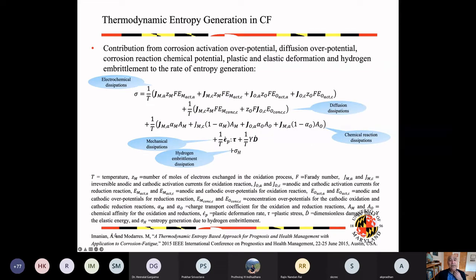So with that, this is another formula which shows the relationship between two different entropies, corrosion and fatigue. Each of the terms is an amount of entropy generation, and this shows the force and the flux of each of them. They are all defined here. For instance, the flux is measured by the overpotential measurement. Essentially, it is the potential in an electrochemical dissipation and oxidation. We can always measure the amount of current and the amount of flux very easily. And each of these terms shows the potential times the current and flux, and then we can calculate the amount of energy dissipated.